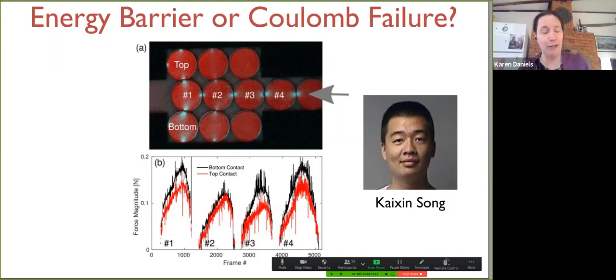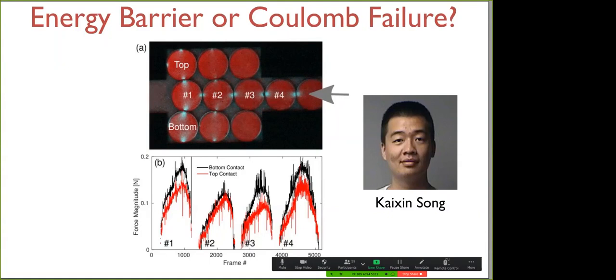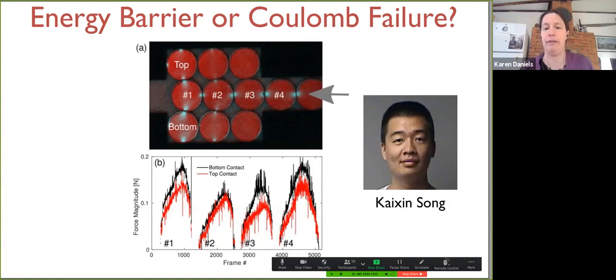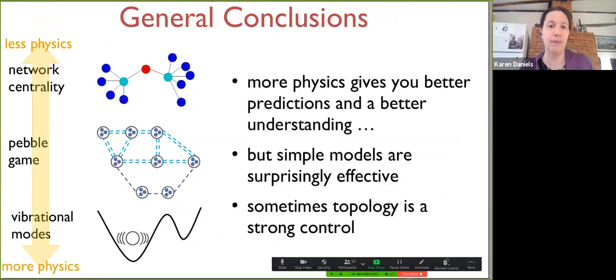magnitude. You can also think of that as energy magnitude, right? It has to squeeze through by compression, okay? And only then later does it fail. So we see elements of both an elastic energy-like behavior and a Coulomb failure behavior. Both of those appear to show up in our data. Okay, and so maybe that is why we're seeing that both of these give very good descriptions for where the rigidity is.